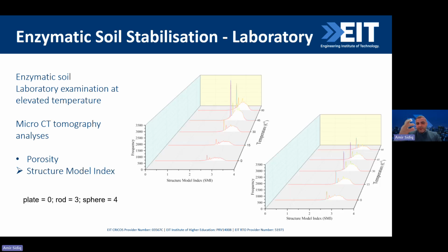I also moved all that material, all those voids, into a different analysis. Now, structural model index is basically when we have a plate-like shape. So plate-like, we have just a crack. It has the XY values, but then there's also a Z. So it's a plate. It's a 3D crack. Rod is basically where the Z value is very, very low, but then X or Y are inversely related. So these are rod-like shapes. And 4 basically means a perfect sphere.